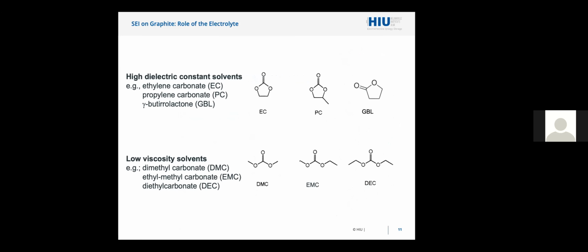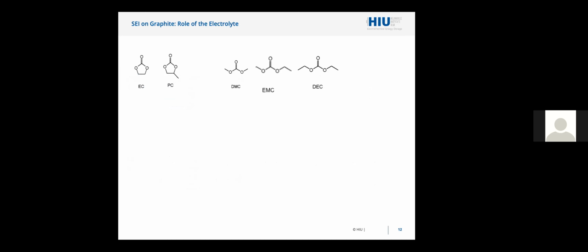So the electrolyte itself has a very big role in the SEI formation. We know that electrolytes for lithium-ion batteries, I guess the next speaker will also talk about this, are usually a mixture of high dielectric constant solvents and low viscosity solvents. And the reason is easy, because we want to optimize salt solubility, which is given by the high dielectric constant solvents, with ion mobility, which is guaranteed by the low viscosity solvents. We need to reduce the viscosity of the electrolyte in order to get good mobility. These are the most common: ethylene carbonate, propylene carbonate, dimethyl carbonate, ethylmethyl carbonate, and diethyl carbonate are the most commonly used solvents for lithium-ion batteries.